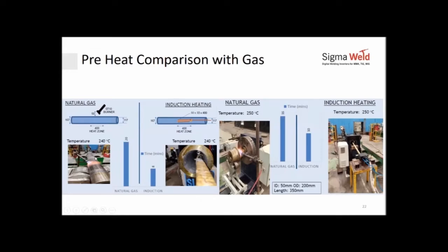This is the burner that was used. And the burner, while the job is rotating and the burner is at a fixed position, when they tried to heat the zone of 400 millimeters, they were able to achieve 240 degrees in 20 minutes. But again, if you can see, with the burner hitting at one point, you will have bright hot spots in some places and not so hot, or not an equivalent temperature of 240 degrees, all across the surface.